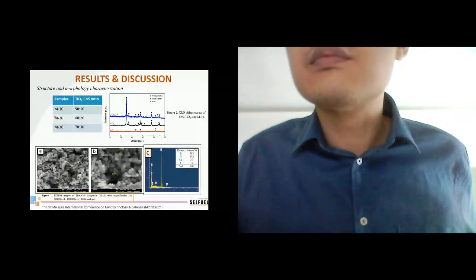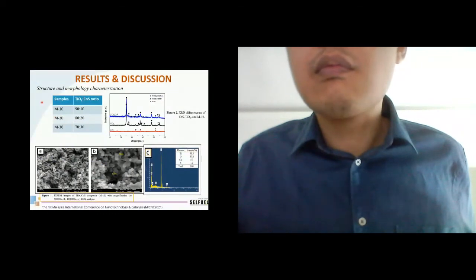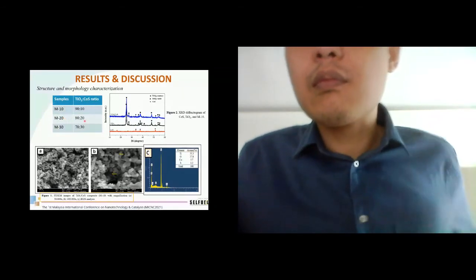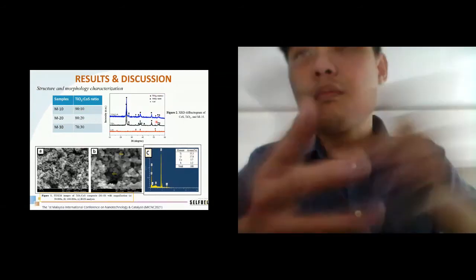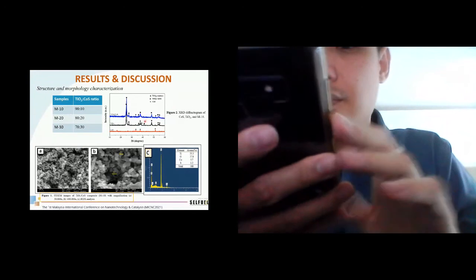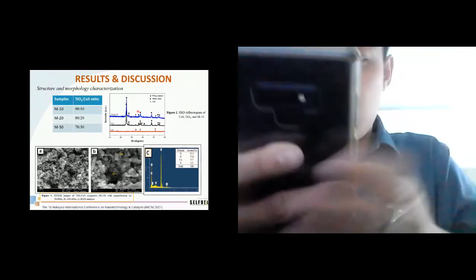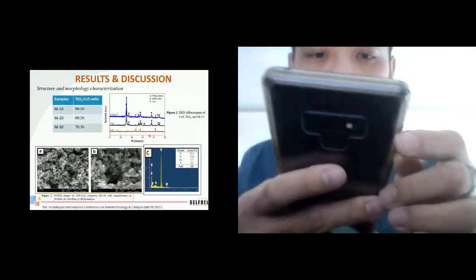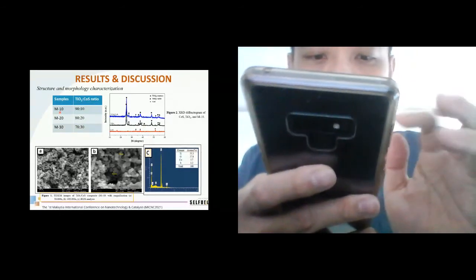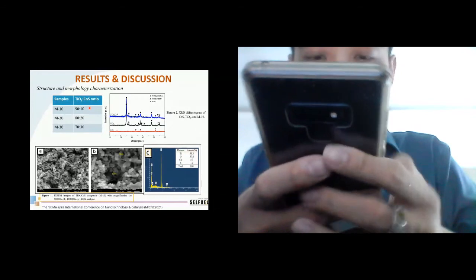Okay, we go to the results and discussion. In this study, we report the performance of three variation compositions of TiO2 and CoS: M10, M20, and M30. The sample names represent the percentage of CoS in the composite. This is the XRD spectral analysis of M10 compared to pure TiO2 and CoS. We can see clearly that the peak of CoS is already present in the M10. Here we only report the XRD for M10, which has the lowest content of CoS compared to the other samples. So if we can detect CoS in the M10, we can show that CoS is also already in the two other samples.